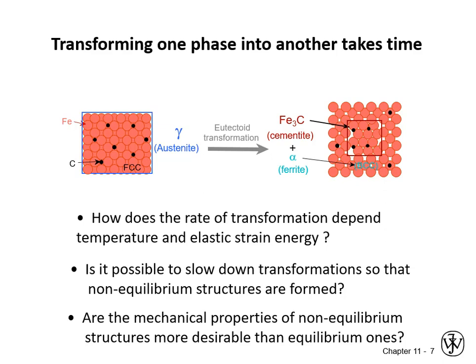When we dip down below the eutectoid transformation, you're going to have regions there that are cementite, the Fe3C intermetallic, in which case 1 in 4 are going to be carbon. So you had to take a lot of carbon from a long ways away and concentrate it all in one place just to get those layers of cementite. So that's an awful lot of diffusion that's going on in order to form that cementite phase, which is one of the reasons that it's easy to inhibit.